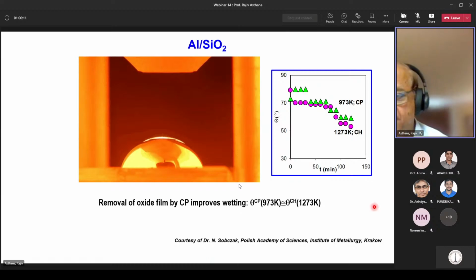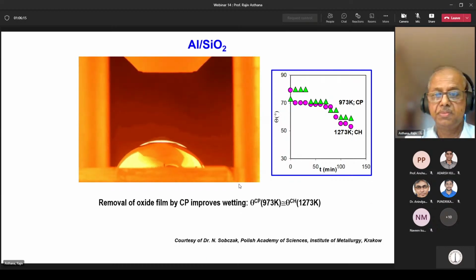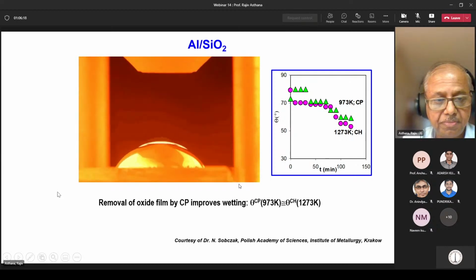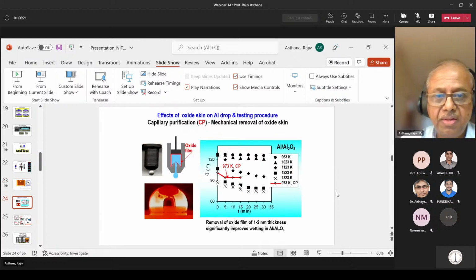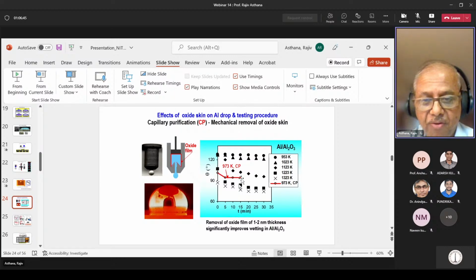You can see the same kind of behavior with other systems. So when you look at aluminum on aluminum oxide and you run different experiments using capillary purification, where you're actually squeezing the droplet out of a capillary, and compare the contact angle values with the value that you obtain by contact heating of aluminum alumina, you can see the effect of removing the oxide film. Again, at low temperatures, you are able to get very, very clean surface and low contact angles that are not possible at fairly high temperature in contact heating kind of a process.